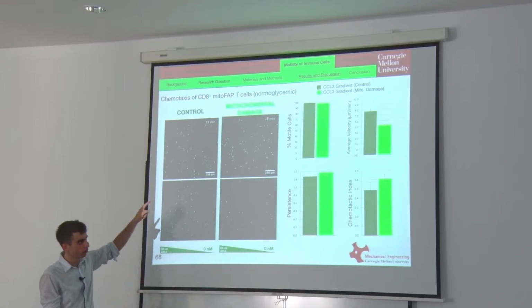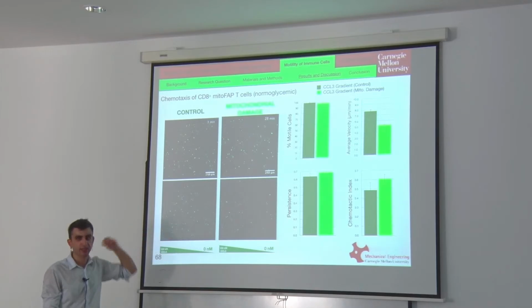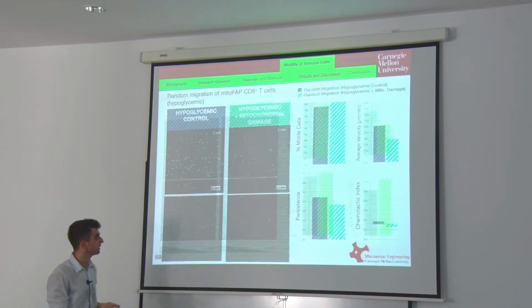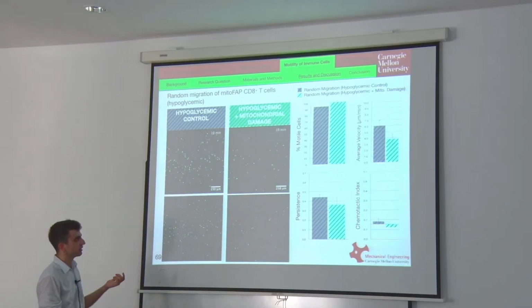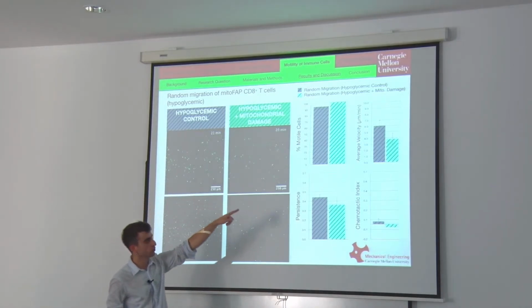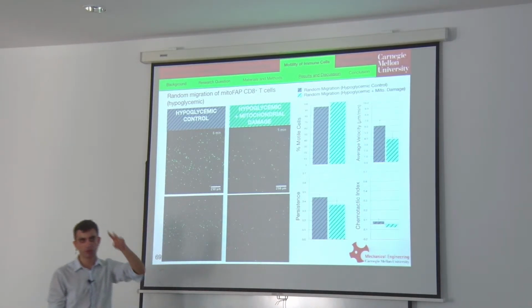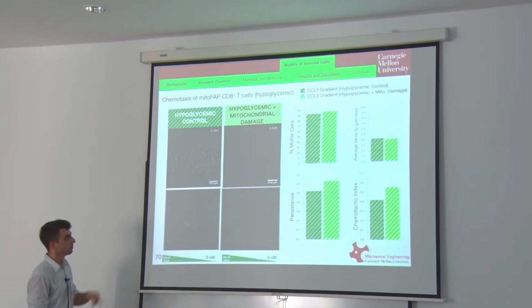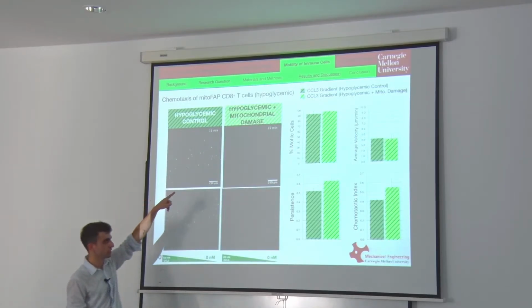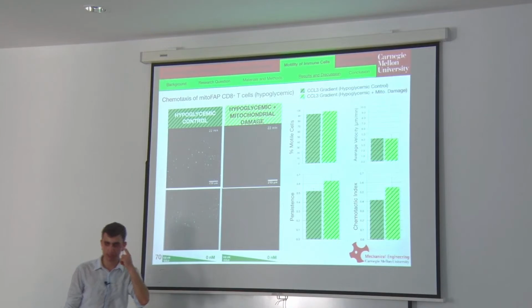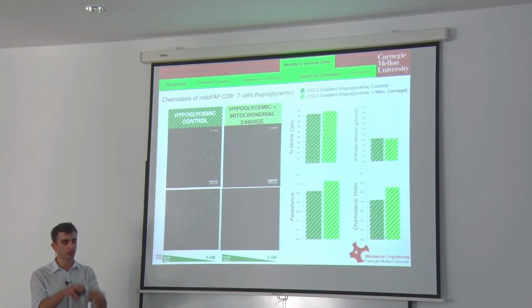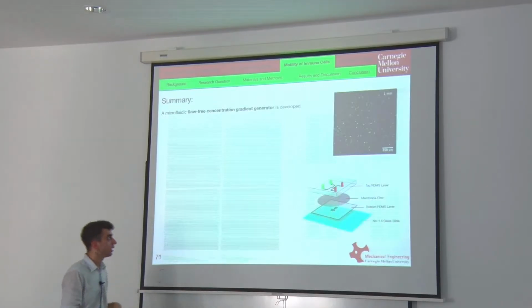And if we do both of them, if we put the cell that has mitochondria damage in a hypoglycemic environment, we see exactly the same thing. The average velocity further decreases because both negative things are together, but the cells that have mitochondria damage have better persistence and chemotactic index. So there's a trade-off between these two, and some of them can be helpful, the other one can be more dangerous, but both of them slow down the cells.